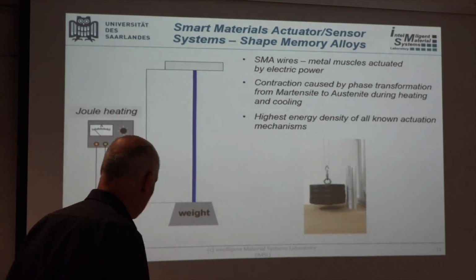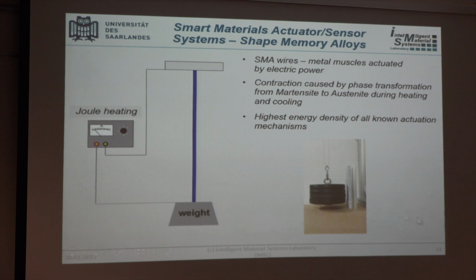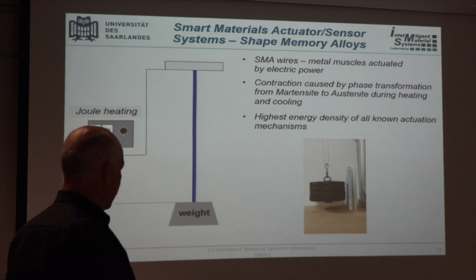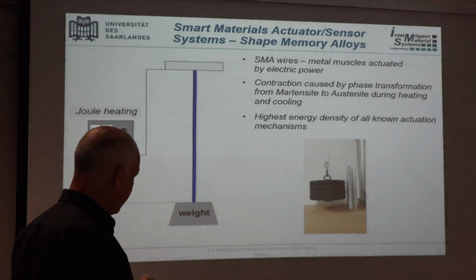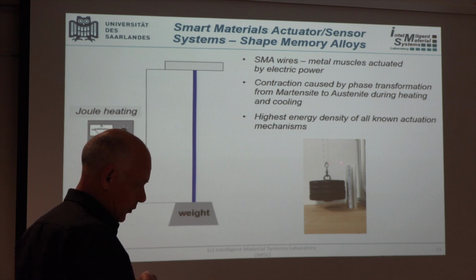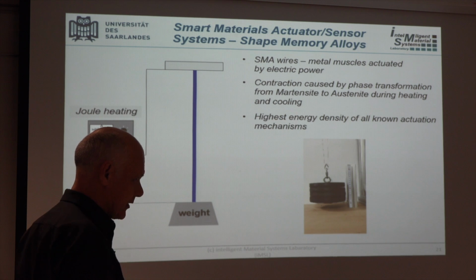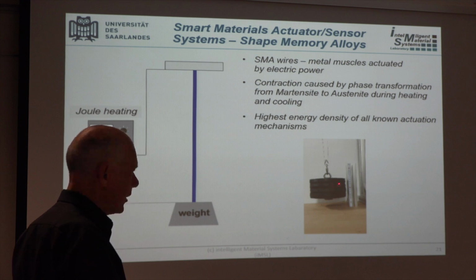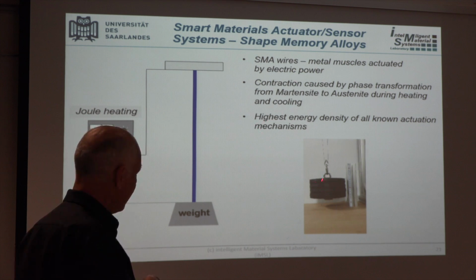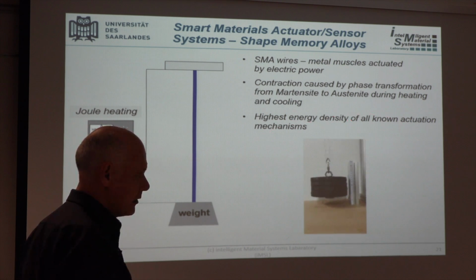So here's a little movie again, showing that behavior. If you look at this, you'll see that we have 10 kilograms that are easily lifted up by a 500 micron wire. So that's 0.5 millimeter in diameter. And just by heating this wire and contracting the wire like an artificial metal muscle, we're performing a lot of work. As a matter of fact, shape memory alloys have the highest energy density of all known actuation mechanisms. Right? So that means that you can perform the most work from a given volume. Why is this?